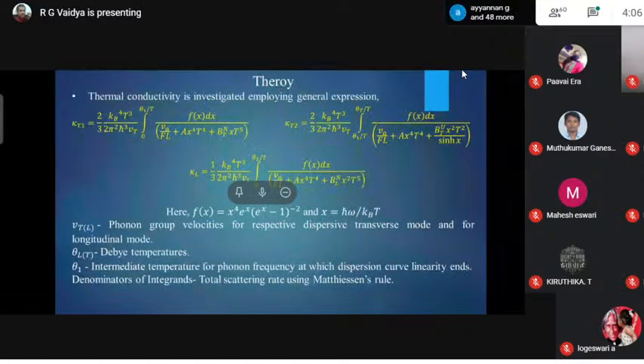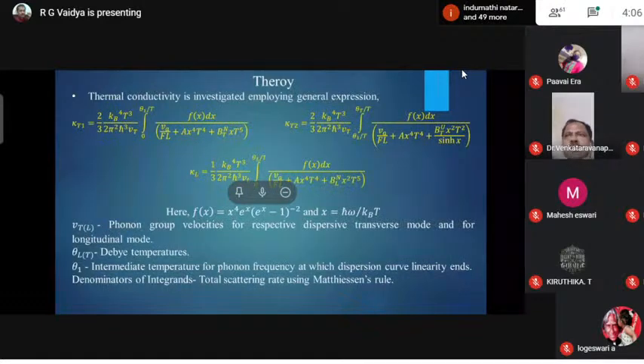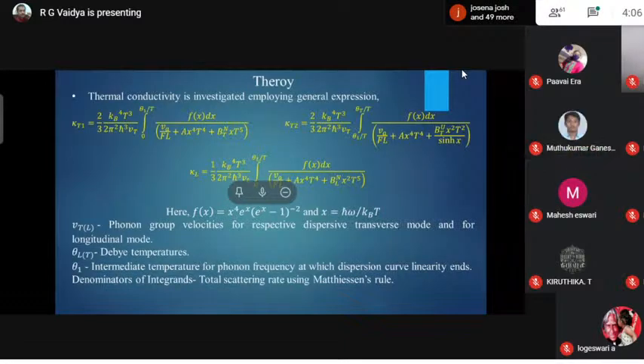These three expressions give the contribution from low frequency transverse phonons, that is KT1. KT2 represents the high frequency transverse phonon contribution to the lattice thermal conductivity. KL represents the longitudinal phonon contribution to the thermal conductivity. And these are extracted from the Holland model, which is based on Boltzmann transport formalism.